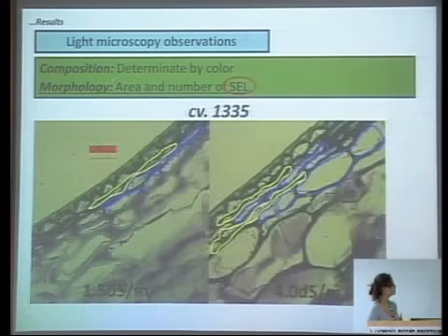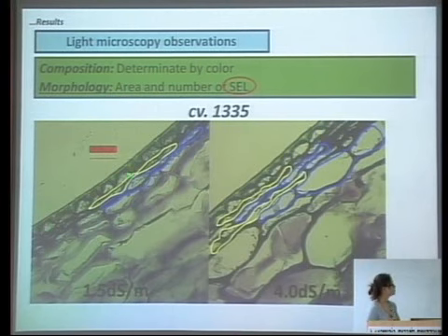But let's remember that the peel is not just composed by the green part of the cuticle, it's also composed by the subepidermical layers. And in the subepidermical layers, we saw tremendous differences. For example, if we grow the cultivars under non-salt stress conditions, we will only have 2 layers of subepidermical. Here's one, and here's the second one. And if we go to salinity, we'll have 1, 2, 3, up to 4 layers. And this was repeated in all the cultivars.